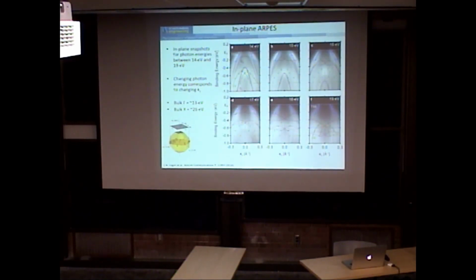So that's a snapshot of this. This is sort of the surface state, this blue and this green. These green ones look like Rashba split states. And then these are the bulk states as we change the photon energy going down.